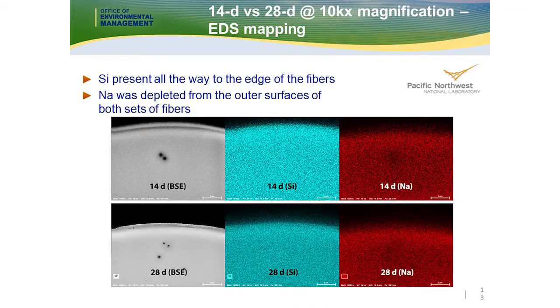Some images of what happens to these things. There was some parallel testing done with drawn fibers exposed under the same conditions. I'm not going to get into a lot of detail now, but you can see from the backscatter image how there is a rind, or an alteration phase, that develops at the surface of the material. This is at 14 days and at 28 days. And you can see basically the loss of sodium at the surface and a little bit of loss of the silica.